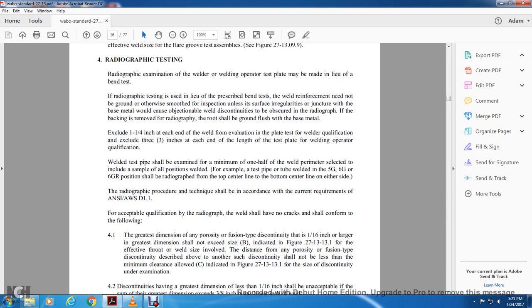The root shall be ground flush with the base metal. Exclude 1 1/4 inch at the end of the weld from evaluation for welder qualification testing. Exclude 3 inches at the end of each length of test plate for welding operator qualification. The welding test shall be examined with a minimum of 1/2 of the welded perimeter selected to include a sample of all positions welded.